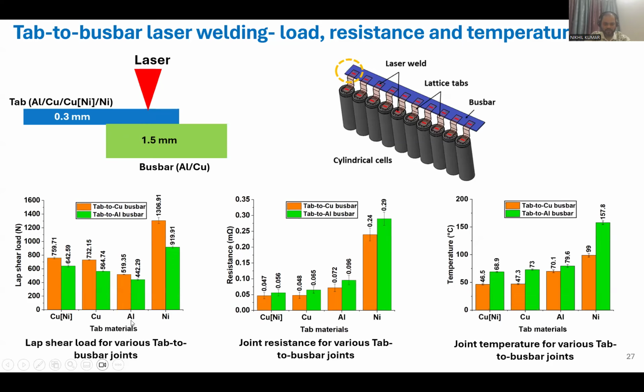So this is aluminum. You can say the aluminum has the lowest strength. Nobody wants lowest strength, but if somebody wants to know what the strength is for aluminum for a particular weld area, because this is welded with the same weld area, like a 5 millimeter circle diameter, they can easily understand the minimum strength that can be achieved using aluminum to copper or aluminum to aluminum combination of welding. From this bar chart, you can say the maximum strength achieved is for the nickel tab to the copper busbar, because nickel and copper are highly compatible materials. There is no intermetallic formation between the nickel and the copper, what I have seen. So they are following all four metallurgical rules.